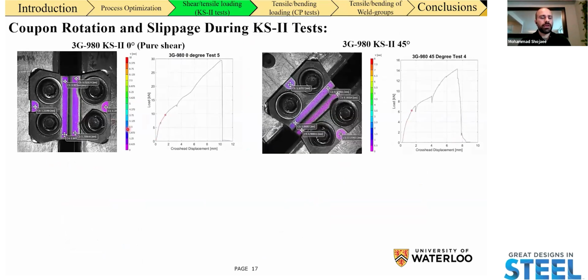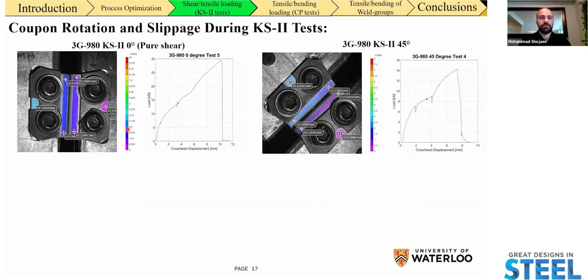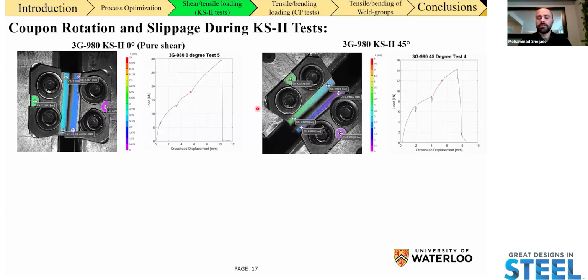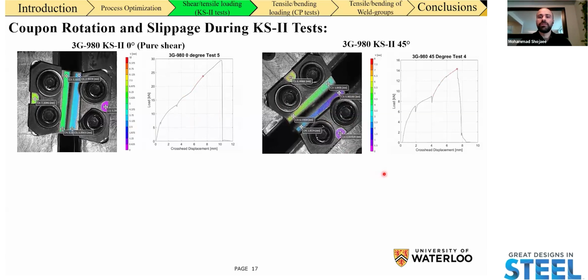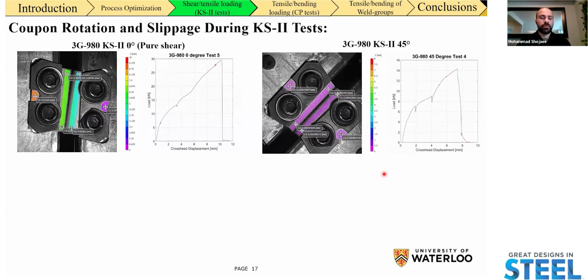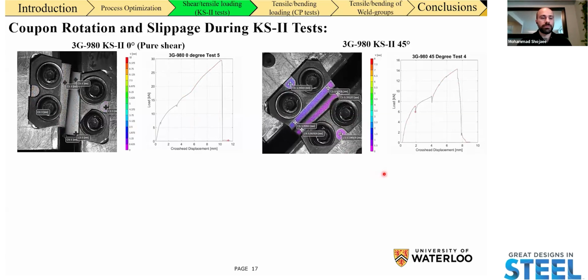On the left, I'm showing a KS2 test at 0-degree loading orientation, representative of the pure shear. And on the right, I'm showing it at 45-degree loading orientation, so ideally equal proportions of shear and tensile load being applied to the spot weld.